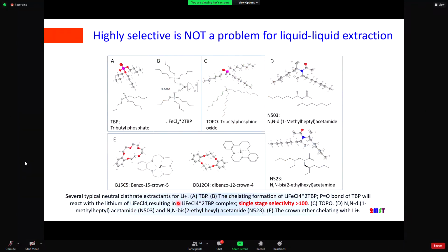However, when you look at liquid extraction, we have plenty of highly selective extractants available. We are working on this hybrid extractant, which has a single-stage selectivity for magnesium and lithium of about 100—if I remember correctly, about 170. So this is much more superior than the nanofiltration or electrodialysis membrane.